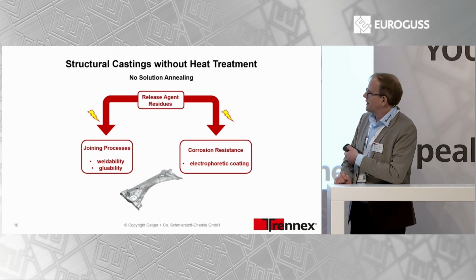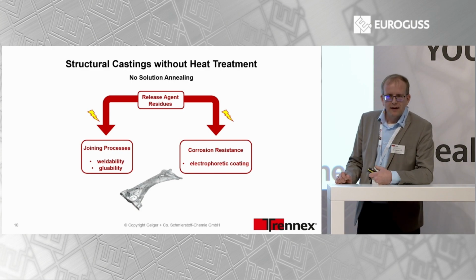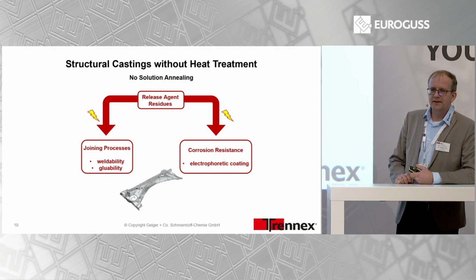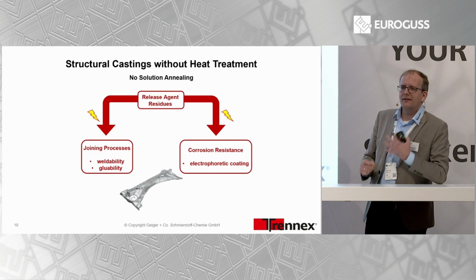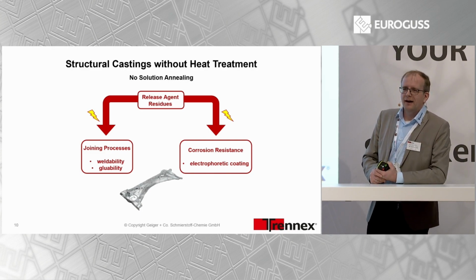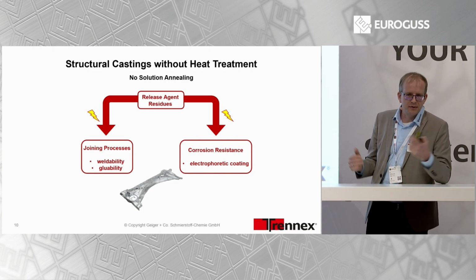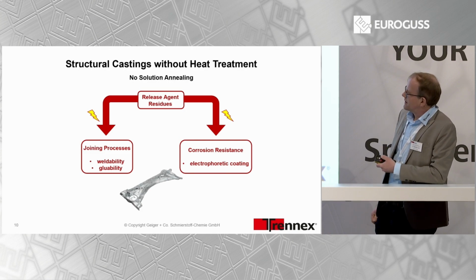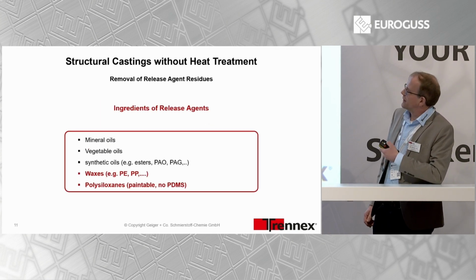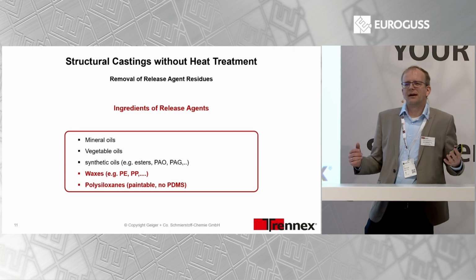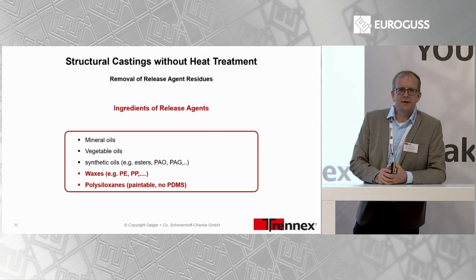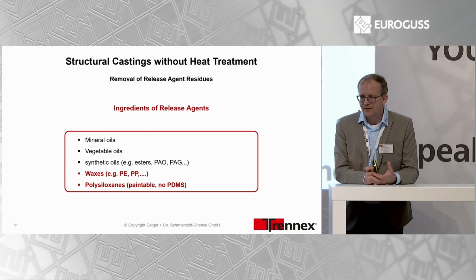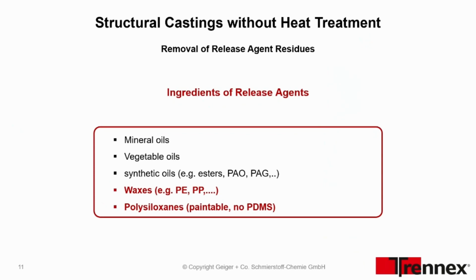especially the electrophoretic coating is very important for the structural castings. They will have problems, and very often we see that with castings that have not been cleaned appropriately, you will fail the corrosion test, for example. So it's very important to get rid of the residues, and so in order to look for an appropriate cleaner, we have to look at the ingredients of a release agent. So what's in a release agent?